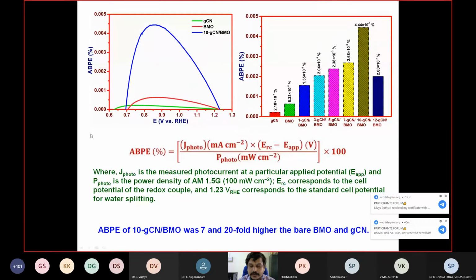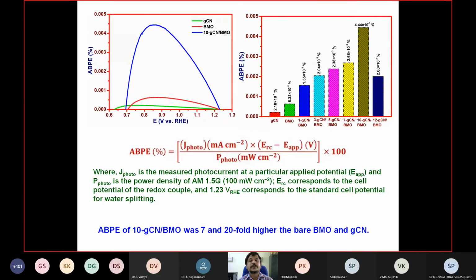So now we have calculated the efficiency of our material. Among the various materials we have developed with different weight percentages of graphitic carbon nitride, this material showed 4.44 into 10 to the power minus 3 percent applied bias photon to current conversion efficiency. This efficiency we have calculated by adopting this formula.